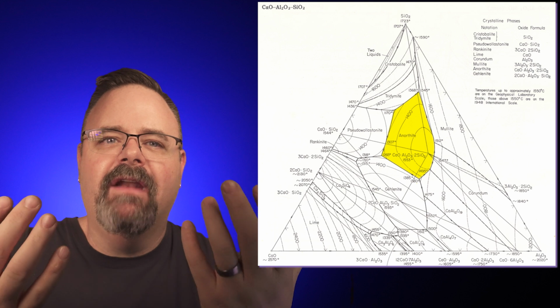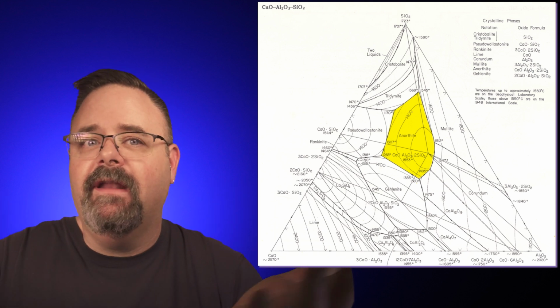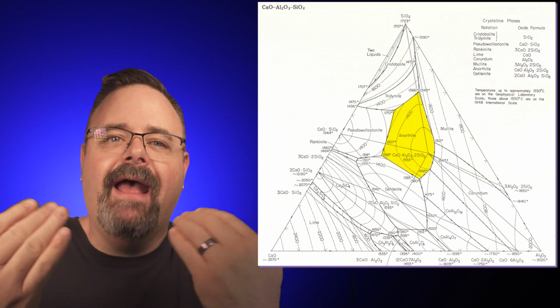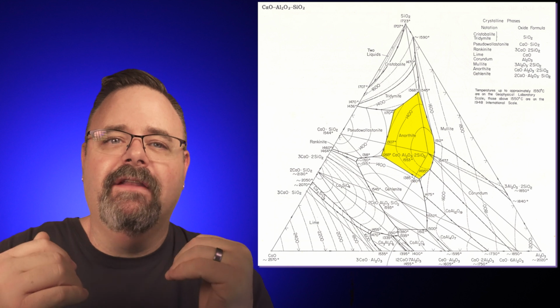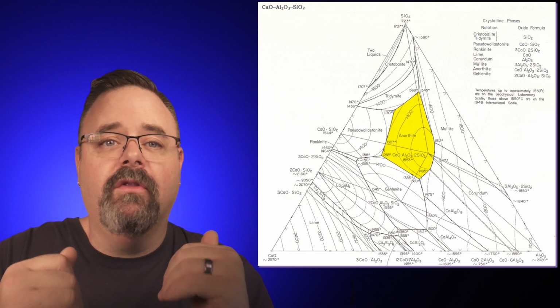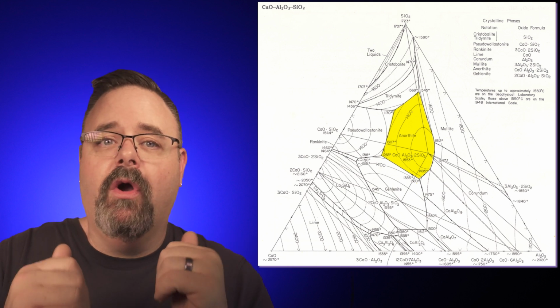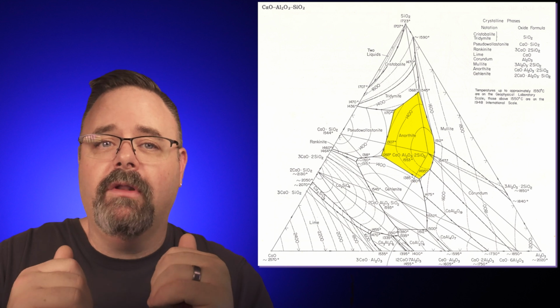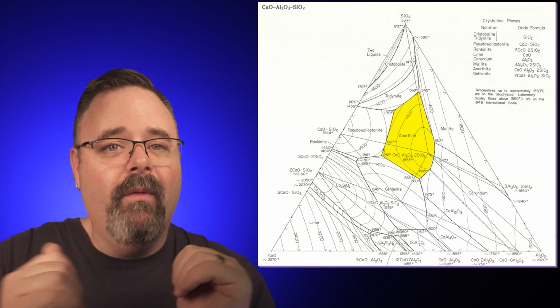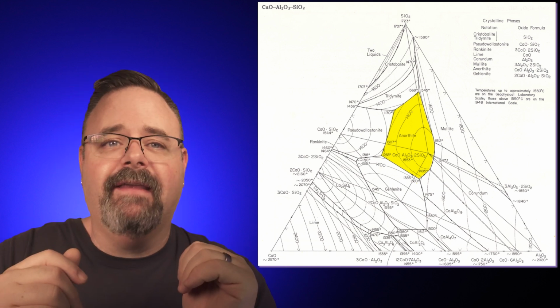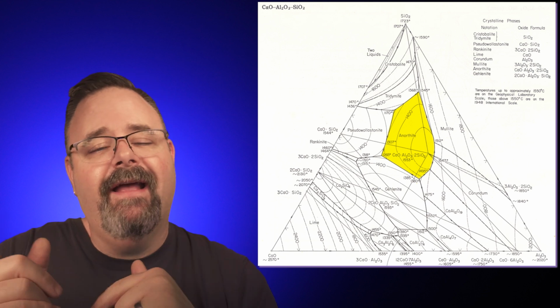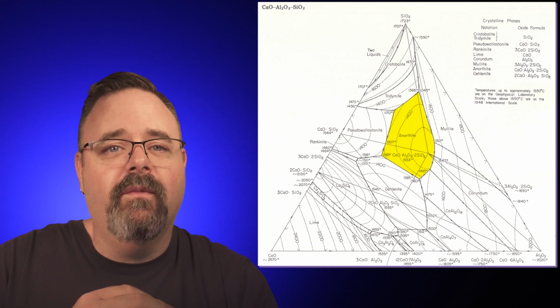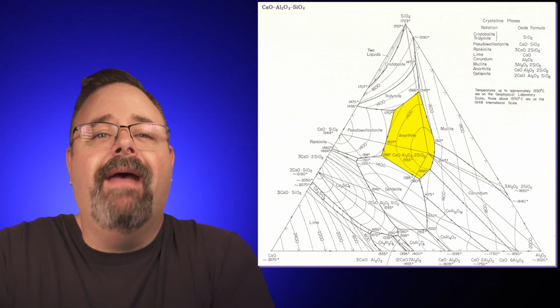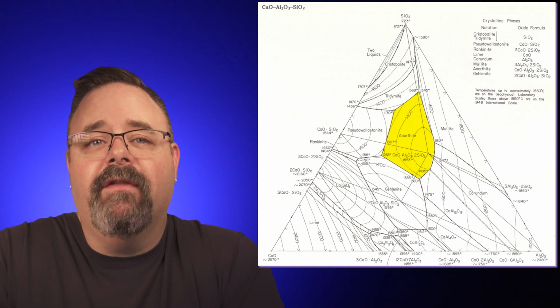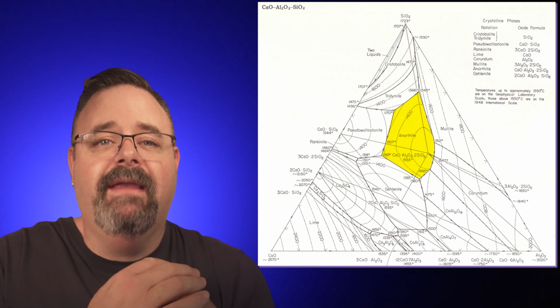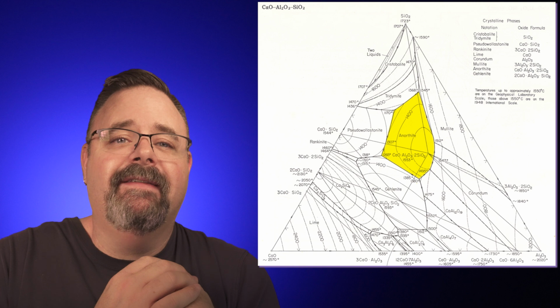And when we get to the end of our firing, the glass is fully melted and the alumina is just fine. But as the kiln shuts down and begins to cool, all of a sudden that alumina needs to find a partner to go home with. It is not going to go home alone. And so it looks around and says, well, I'm not welcome in the glass. Hey, you excess calcium, and I'll take a little bit of silica. Let's all get together and make a crystal so that we can find stability. And the crystal that a matte glaze using calcium forms is anorthite, and that's specifically the crystal that we get. And it's going to do it exceptionally consistently.